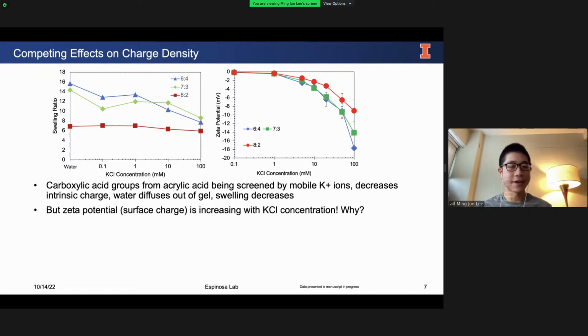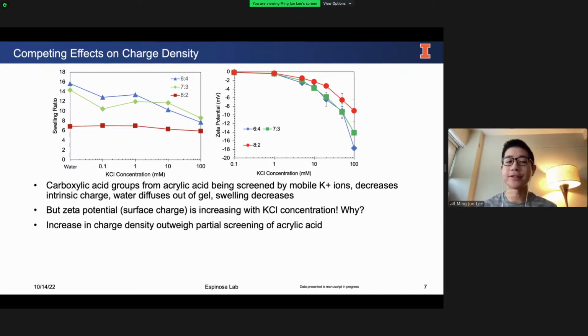But wait, I just said that the charges are being screened by the mobile ions. So why is the zeta potential getting stronger and stronger, more negative? This doesn't make sense. I think what's happening here is that there are actually competing effects between these phenomena. As the volume of the hydrogel is decreasing, the charge per unit volume, and therefore the charge per unit surface area of these hydrogels, is increasing. So the charge density is increasing, and that outweighs the partial screening of the acrylic acid, leading to the stronger zeta potentials that we see here.